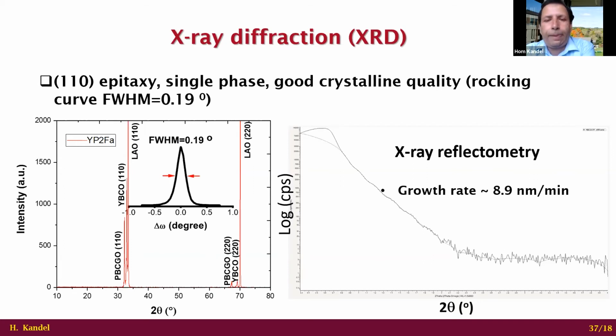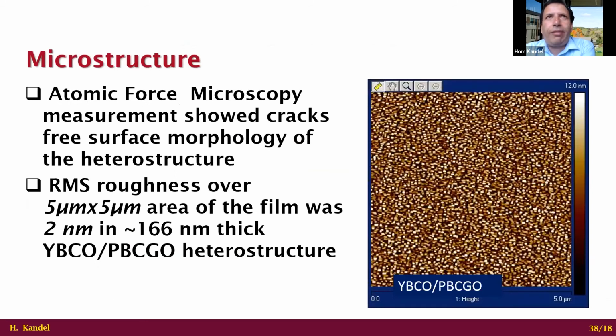Next slide, please. We need an extremely thin, extremely uniform surface morphology in our heterostructure. For that reason, we use AFM, atomic force microscopy, to measure that. The RMS roughness of one of the samples that one of my students grew last time was 2 nanometers over 166 nanometers of this heterostructure.